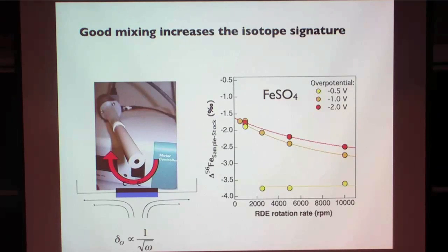We can do that by mixing mechanically with a mixer at the bottom of the potentiostat. But a cleaner way to do it, in a way that's been developed in the electrochemistry community, is by using a rotating disc electrode. So the electrode is actually at the bottom of a cylinder, almost identical in size and aspect ratio as this laser pointer, and it now rotates about this axis. The faster it rotates, the more material is pulled up hydrodynamically to the bottom. And so you can run a series of experiments under controlled fluid transport to that electrode. And so we know the flux of material going to the electrode as a function of rotation rate. So now not only are we just mixing, but we're mixing in a very precise way.